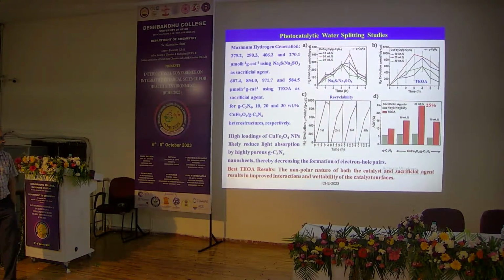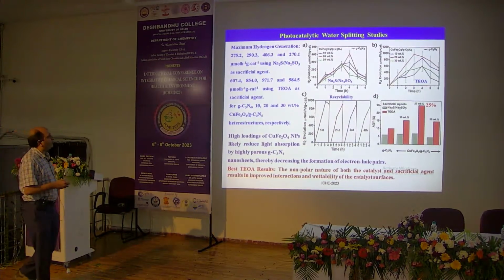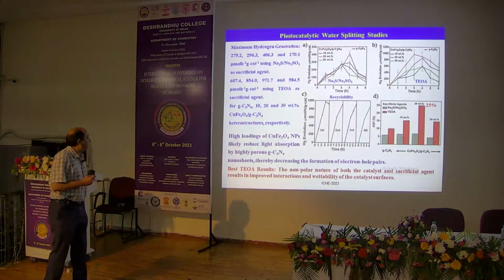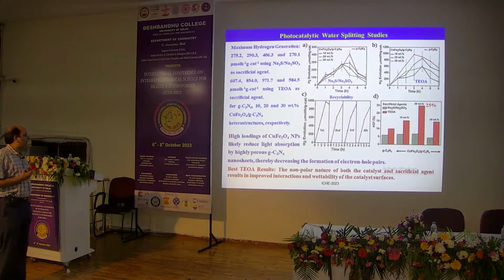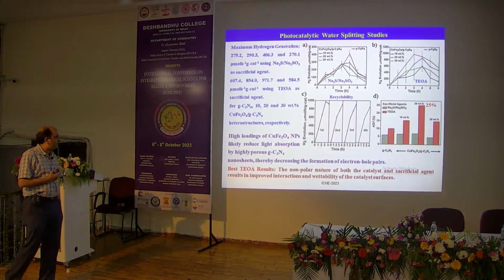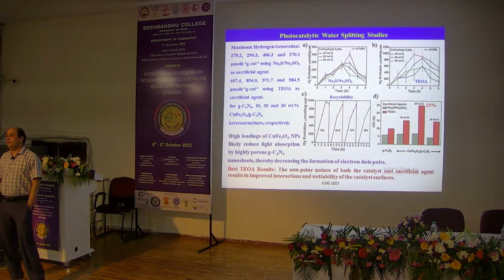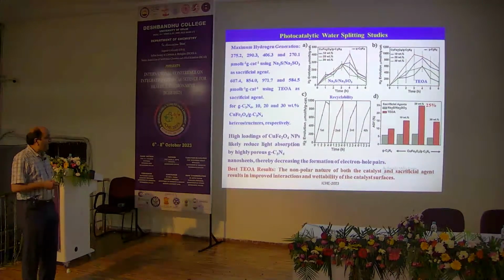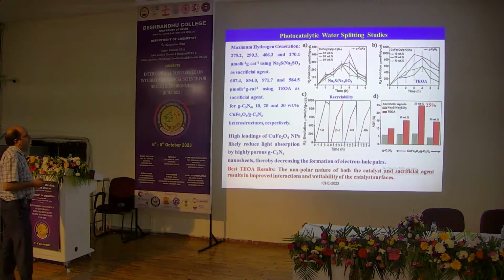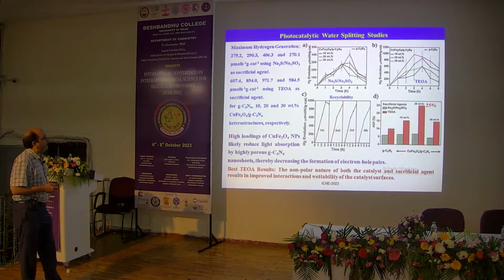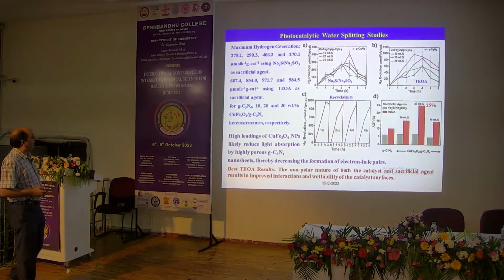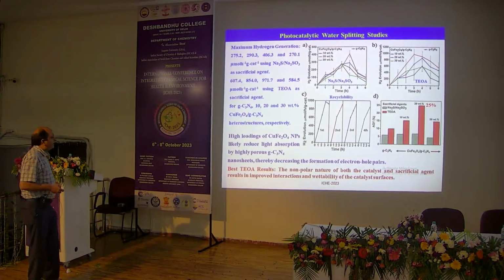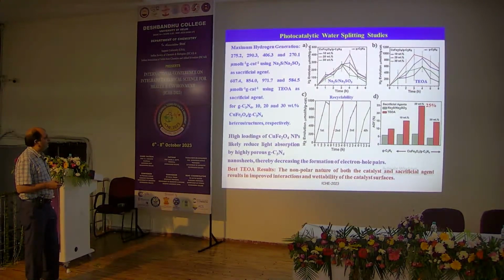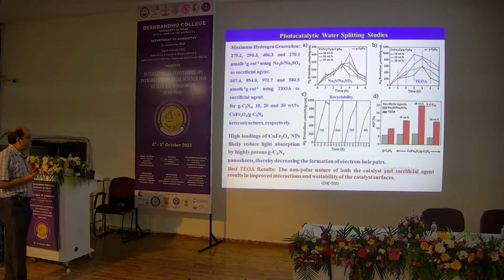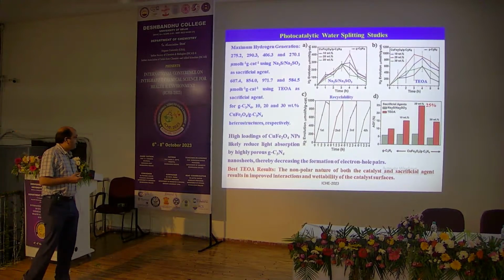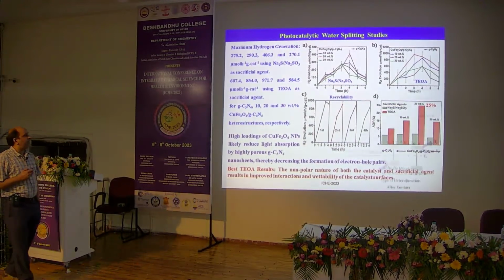graphitic carbon nitride. This is because a high loading of copper ferrite over graphitic carbon nitride can likely reduce the light absorption by the highly porous graphitic carbon nitride nanosheets, and therefore decrease the formation of electron-hole pairs. And we got a high amount of hydrogen by using triethanolamine. This is because of the non-polar nature of both the catalyst as well as the sacrificial agent, which results in improved interaction and wettability of the catalyst surface.